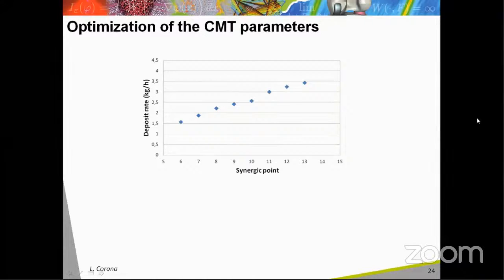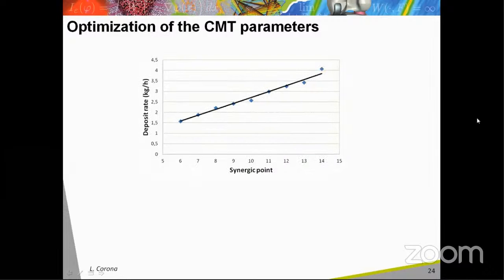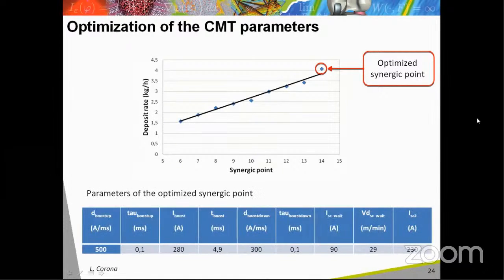The optimization of the process parameters has been conducted in order to increase the deposit rate without creation of porosity and sputters. This graphic shows the deposit rates obtained with the synergic points of the CMT process for a steel wire. The synergic points correspond to parameter sets pre-recorded in the welding process for a given material to obtain a stable and regular metal transfer. One can see that the maximum deposit rate allowed with this parameter set is about 3.5 kg per hour. Thanks to the optimization of the process parameters, a new synergic point has been added, allowing a deposit rate of more than 4 kg per hour. That corresponds to an increase of about 20% compared to the maximum deposit rate allowed with the pre-recorded parameters.